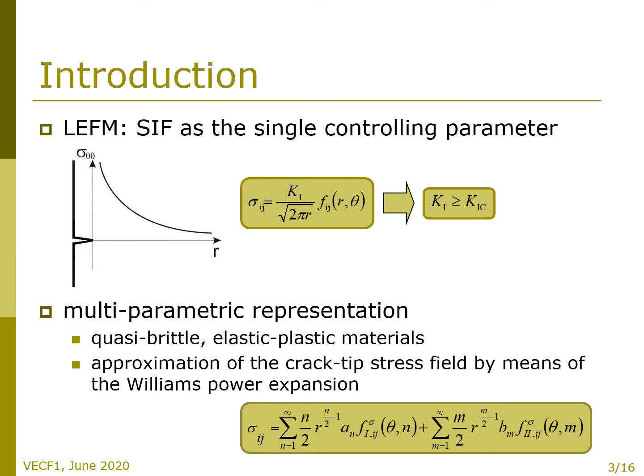The thing is that it has been shown in the recent years that the classical linear elastic fracture mechanics concept that uses the stress intensity factor as the single controlling parameter for assessment of fracture behavior of specimens and structures with crack is not able to describe the fracture processes under specific conditions, especially when the fracture occurs in a more distant surroundings around the crack tip, which is typical, for instance, for quasi-brittle or elastic plastic materials. Then, a multi-parameter approach seems to be a good choice. It assumes approximation of crack tip fields by means of the Williams expansion, considering more initial terms of the power series.